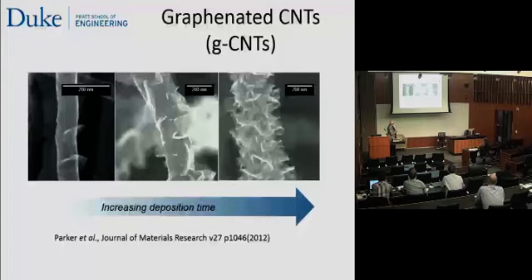So we have a more or less clean carbon nanotube, which is full of carbon walls, just like a sheet of graphite, for those of you who don't know it, wrapped around itself to make a cylinder. And it's got smooth walls, except a couple of initial flakes shown here. And then all the way over to here, which is covered with these graphene nanoflakes. And these graphene nanoflakes have very high charge density edges and are very reactive. So what we're doing here is we're combining the three-dimensional network of a forest of nanotubes, or a network of nanotubes, with the edges of the graphene.